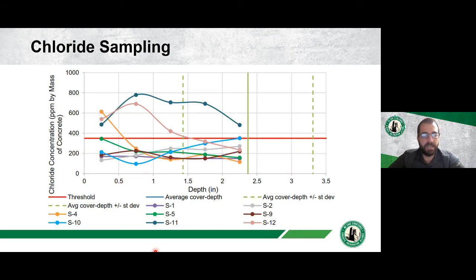Did some chloride sampling. This building is relatively close to the water, so you might get some atmospheric chlorides off the water. You can see the chlorides are much lower, but there is still a little bit of chloride in the concrete. Here's that 350 line. You can see most of the samples are well below it, but we do have some exposure. One high level, so this is probably near a crack or something where chlorides have gotten in from the air.